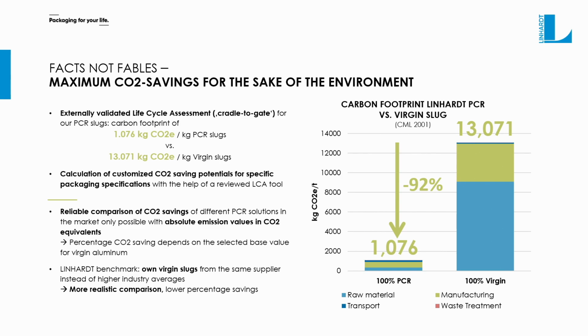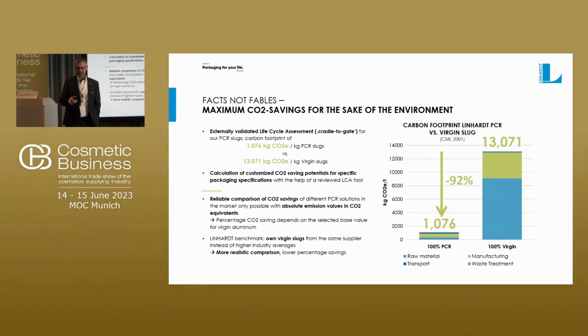Right now, our aluminum mix, which we mainly source from Europe but also from other continents, has approximately 13 tons of CO2 emissions per ton of aluminum. And the PCR that we purchase, because it's remelted and the molten material is directly turned into the material, only has approximately 1 ton of CO2 per ton of aluminum. So we did our own life cycle assessment, cradle to gate, and we had that result validated by Hochschule München, by Professor de Kurt, in order to make absolutely sure that our calculations were correct.